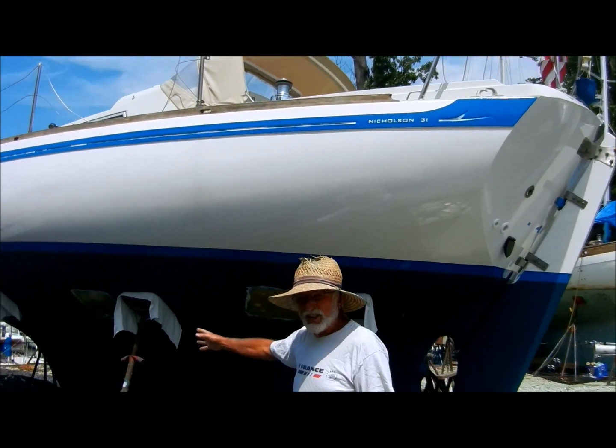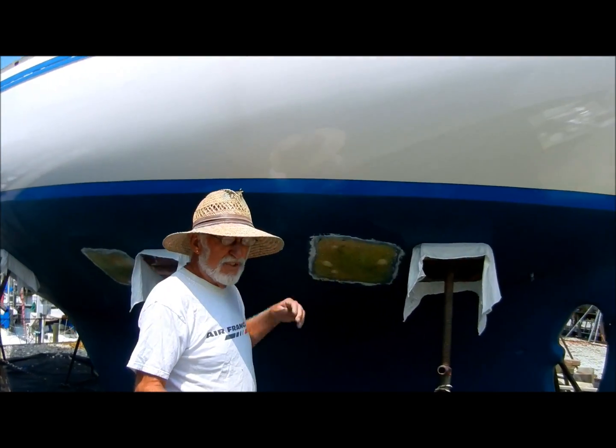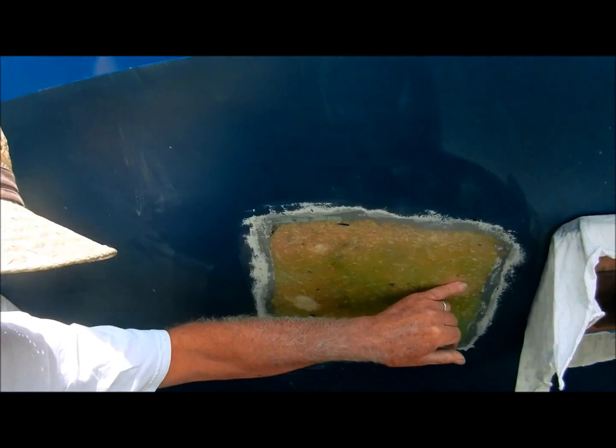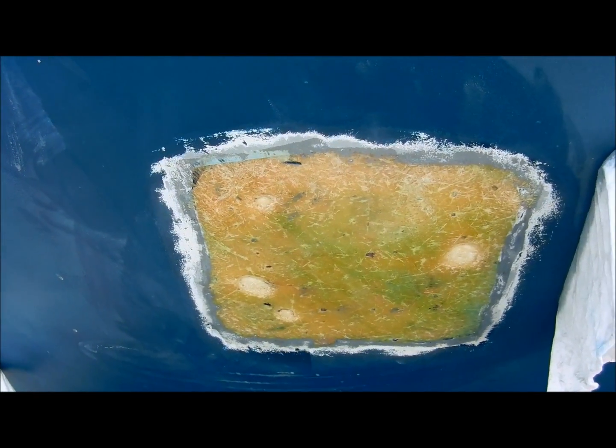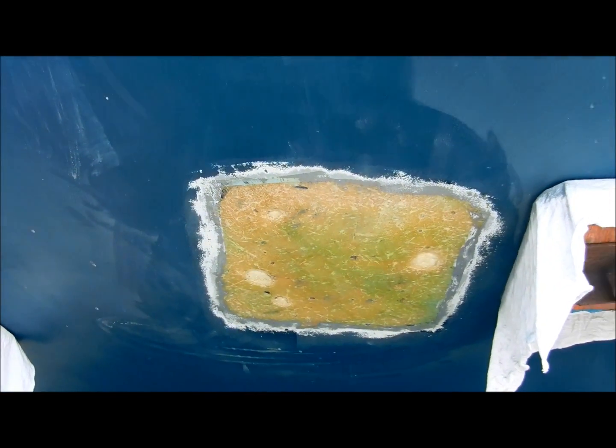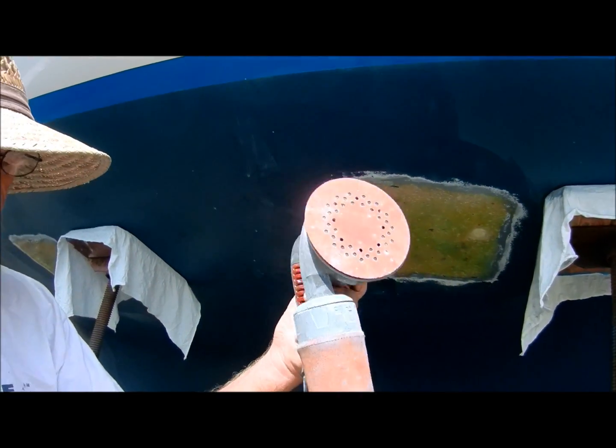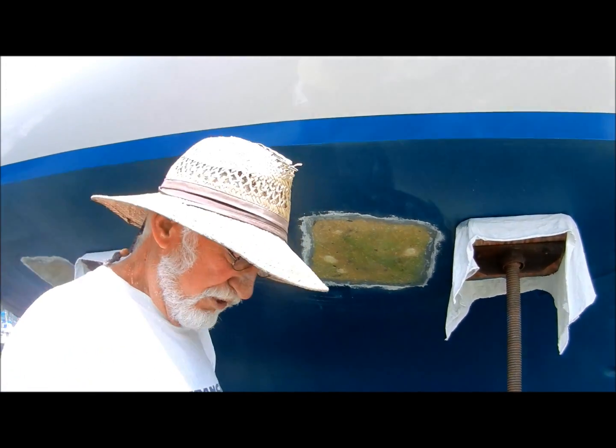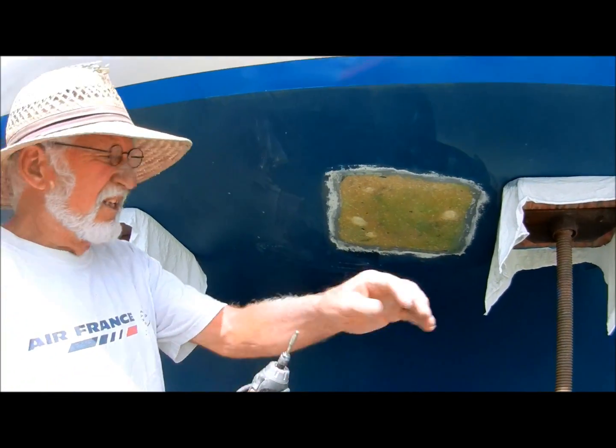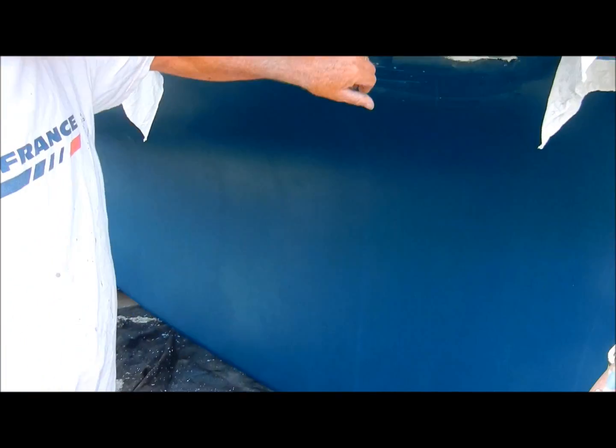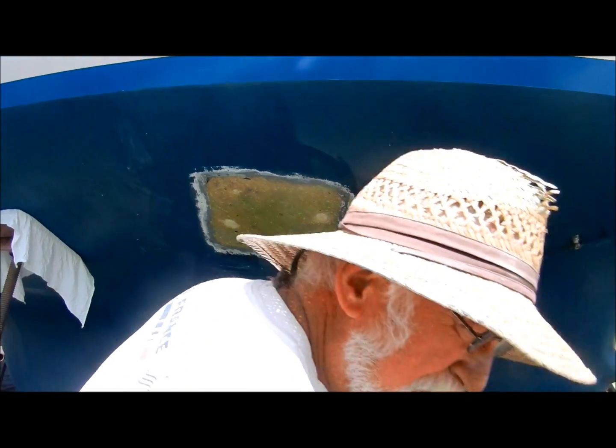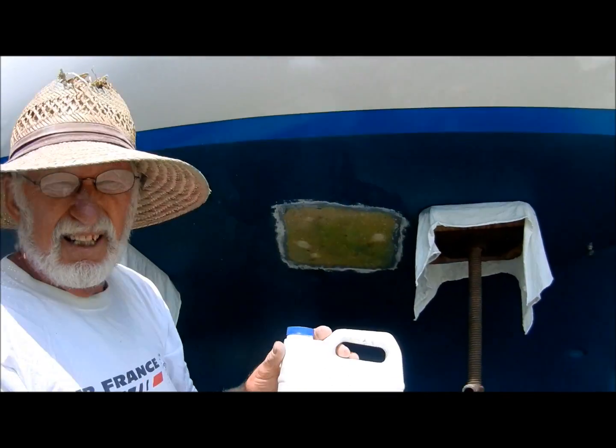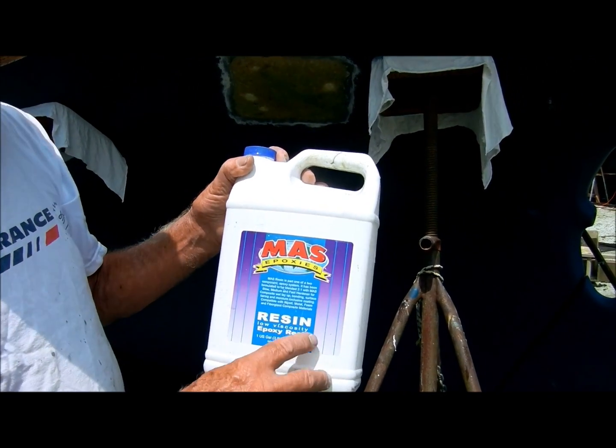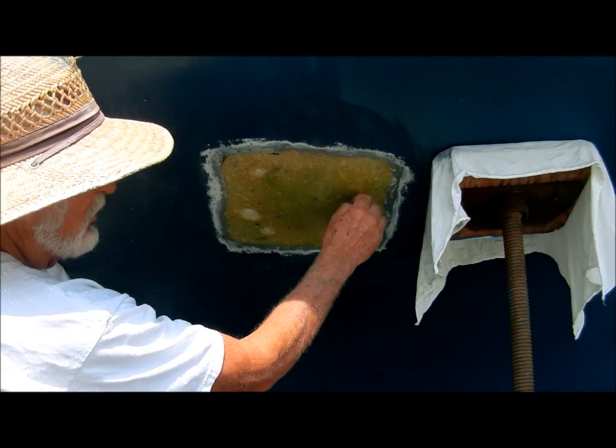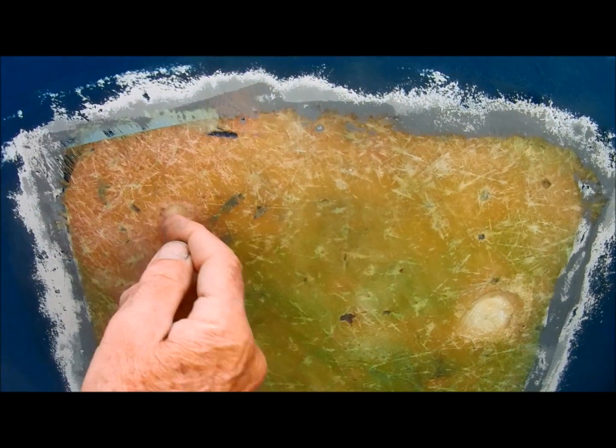Okay. When the bottom was stripped a month ago, we found 500 blisters on the bottom. We ground the bottom paint off first using a grinder, and then a sander like this. When the bottom was clean, we used a Dremel tool like this with a wheel on it to gouge out the blisters in this manner. When we'd finished gouging out the blisters, we used a West System epoxy resin, low viscosity, which means it's quite watery, and it will seep into the cavities and the laminations, the voids between the layers of glass.